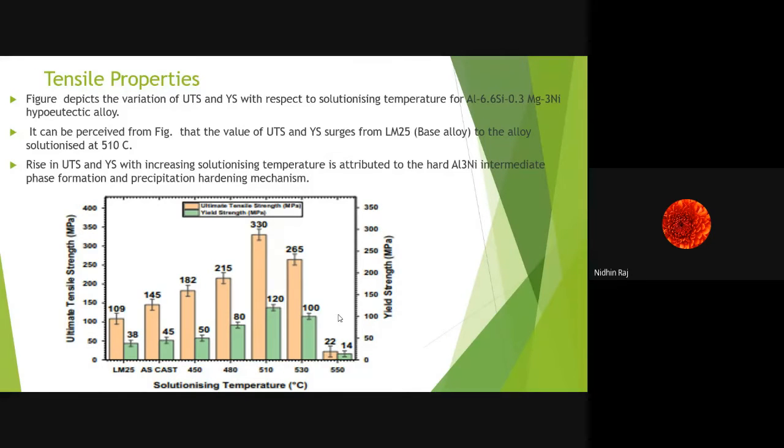This decrease in the value of UTS and YS from 510 to 530 is due to the reduction in vacancies causing formation of fewer aluminum nickel precipitates. A further decrease in strength is owed to the formation of casting imperfections such as shrinkage, porosity, etc. that are observed during casting. These results are found to be in terms with studies conducted in the previous literature also. The previous studies also confirm the same kind of trend in...